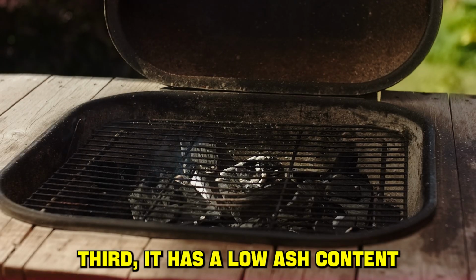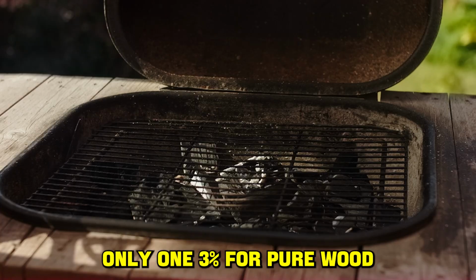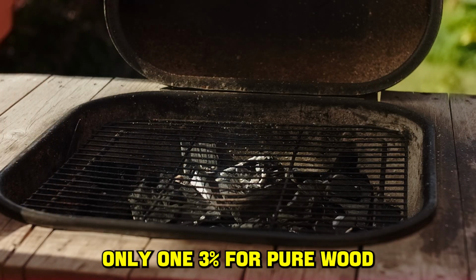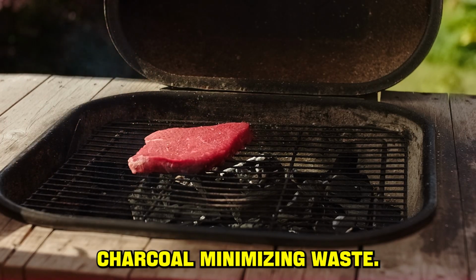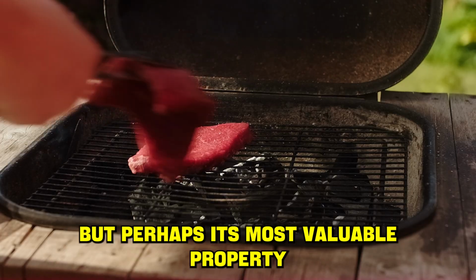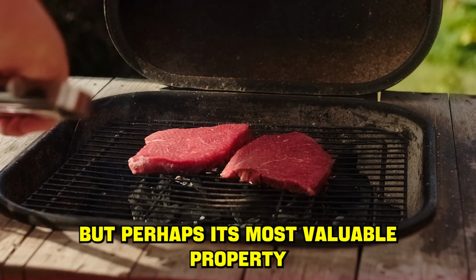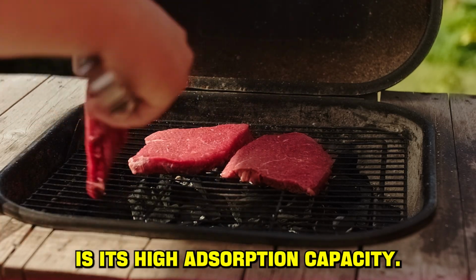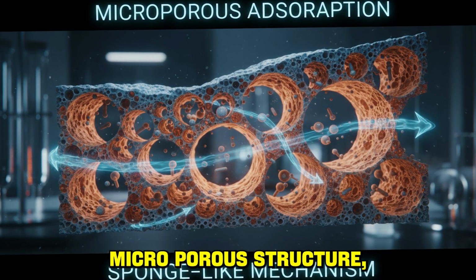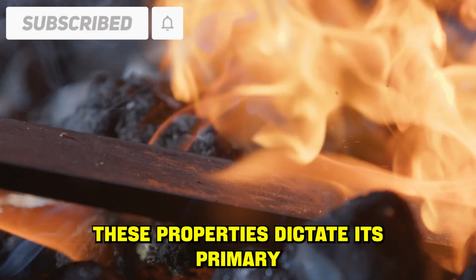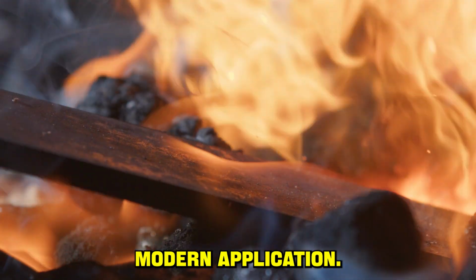Third, it has a low ash content, only 1–3% for pure wood charcoal, minimizing waste. But perhaps its most valuable property is its high adsorption capacity due to its developed microporous structure, which works like a sponge for gas molecules and dissolved substances. These properties dictate its primary modern application.